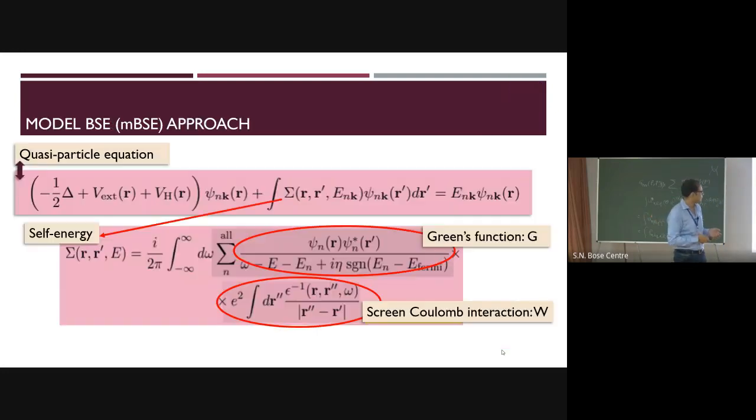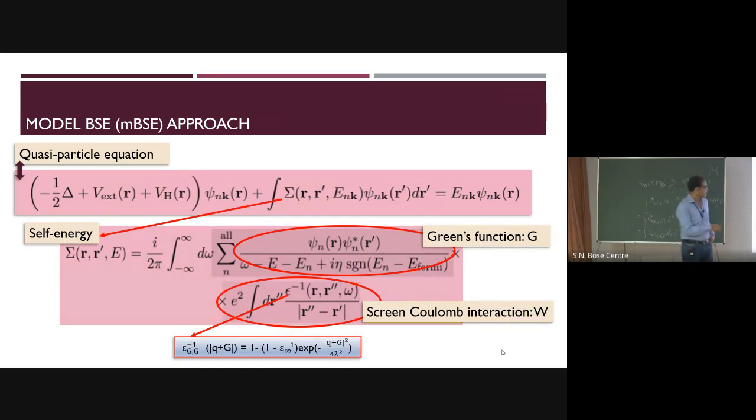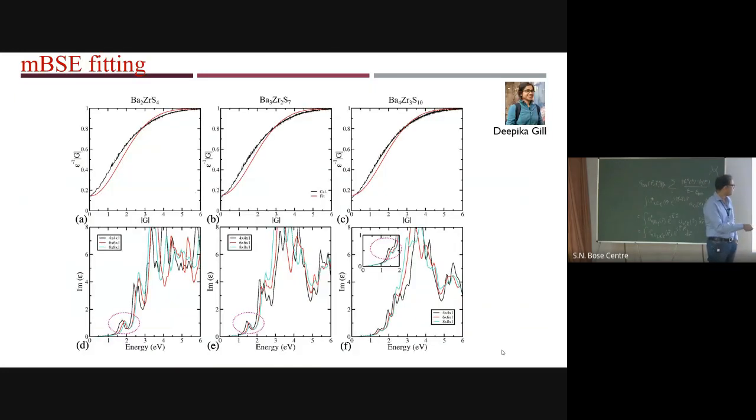So what we do is the following. This one we replace with an analytical function which looks like this. This one we compute with density functional perturbation theory, and this lambda we calculate from here. This is what we plotted using GW, and this is what we fitted, and that's how we compute lambda. Then if you put it back there, that's how you can converge this peak.